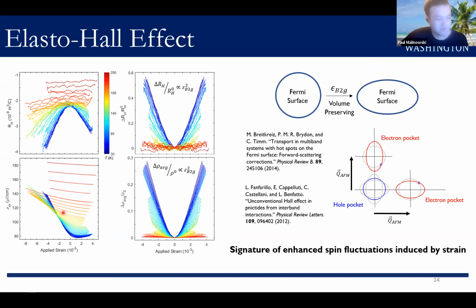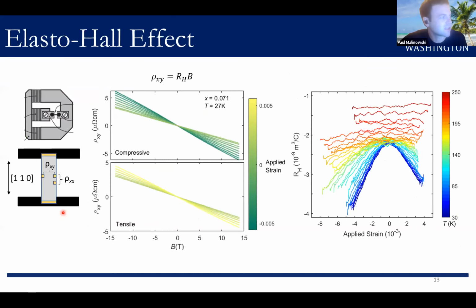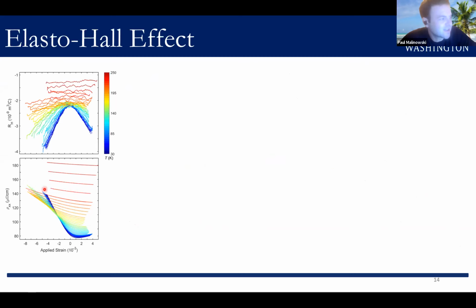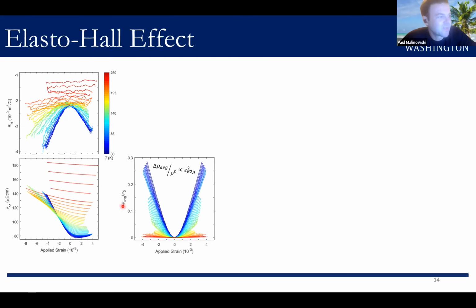So the thing is that the way that we're doing this measurement, we don't have direct access to rho YY. Although, according to the symmetry, when you're at compressive strain, you're measuring one component of the resistivity. And when you're on the tensile strain side, you're measuring another component. So basically what we can access is the average resistivity, that would be rho XX plus rho YY. And then by anti-symmetrizing this data, we could also access rho XX minus rho YY.